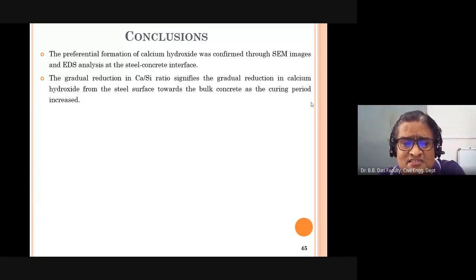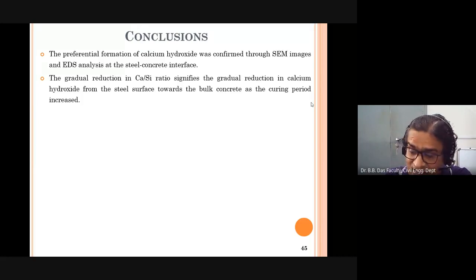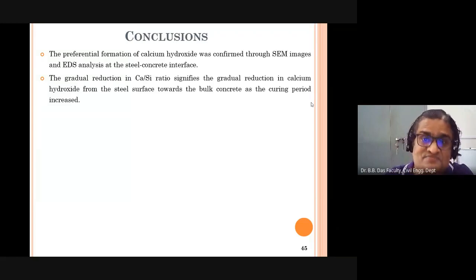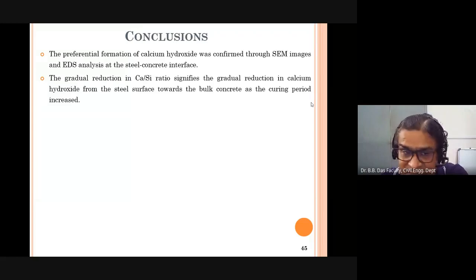Second is the gradual reduction in Ca by Si ratio signifies the gradual reduction in calcium hydroxide from the steel surface toward the bulk concrete as the curing period increased. Well, curing period is the key. Remember, I'm telling you again and again, the curing plays a decisive role. Even this measurement was only at a micro level, but it is having a decisive influence.